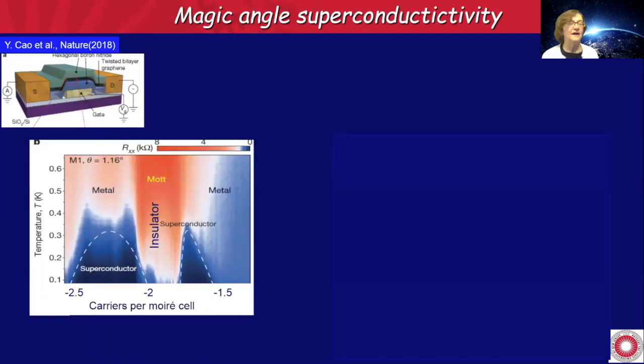So the group of Pablo Jarillo-Herrero at MIT used this technique to make a device, to make a transistor. Here we have the twisted bilayer graphene, nicely encapsulated and protected with boron nitride. You have source and drain electrodes. You have a gate electrode, so you can change the Fermi energy. You can throw electrons into your sample or pull them out just by the gate voltage, and you can measure its transport properties.